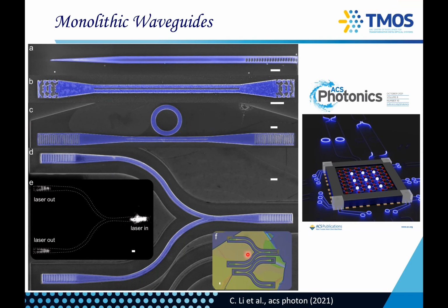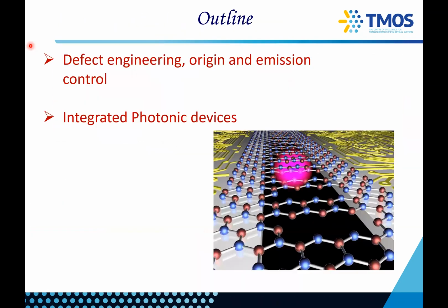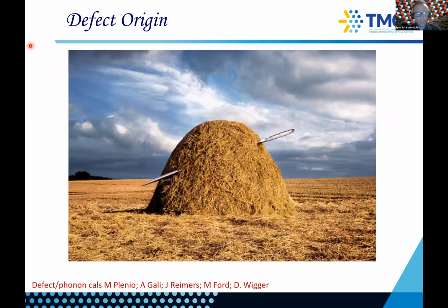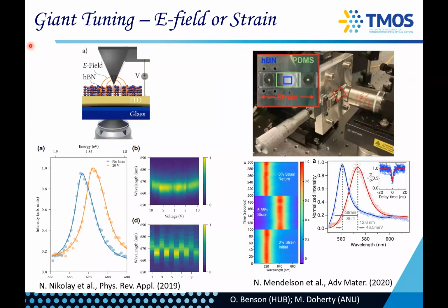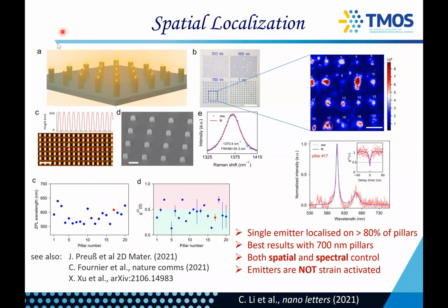Okay, great. My question was about the nanopillar structure. I didn't quite understand the structure and the way you manipulate the boron nitride crystals. You mentioned that 700 nanometers was working better, and this is the pitch between the pillars, or what do you mean? So the pillars are made from silicon oxide, and what we do is we grow hBN directly on top. We don't put the crystal on top, we just grow. You can't see it from the image because it's conformal, but there is actually a layer of hBN here, and the 700 nanometers is the diameter of the pillar.